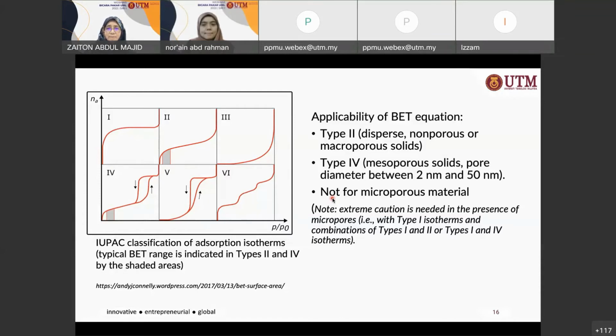Now most of you who, for example, have worked with determination of surface area know that if you have micropores present, you have to do the alpha S plot or the t-plot to determine the micropore area. You cannot get it from the BET surface area. So, let's say you have a combination of type 1 and type 2 or type 1 and type 4, you have to look at the pore size distribution, the BJH desorption pore size distribution, and from there, you have to run the alpha S plot or t-plot to determine the micropore volume and the micropore area. You have to take into consideration the S BET and S external, and then subtract to get the micropore area. So that is another one. You cannot get it directly from the BET surface area.